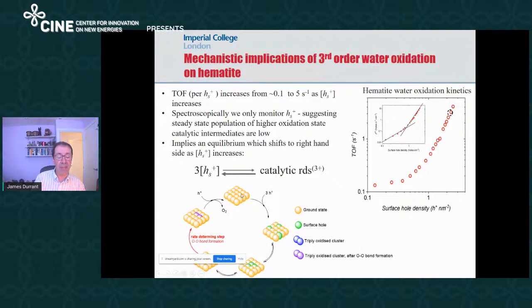and it suggests that the rate determining step, I'm sorry, this thing always gets in the way. Oh, there, let's go. The rate determining step requires 3 holes to come together to oxidize what we believe to be a dimer of metal centers to make the OO bond as a rate determining step, and then the final hole comes on to allow oxygen to be released. And so what we have, the idea is an equilibrium between these surface holes and the rate determining step, and as we increase the density of holes, the equilibrium shifts to the right hand side and the reaction accelerates.